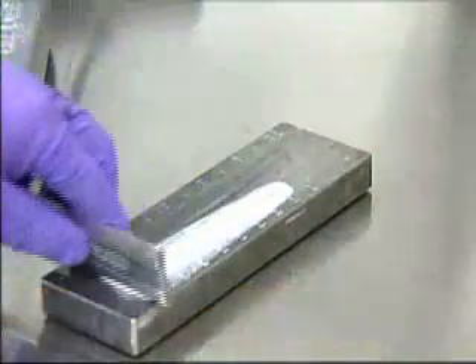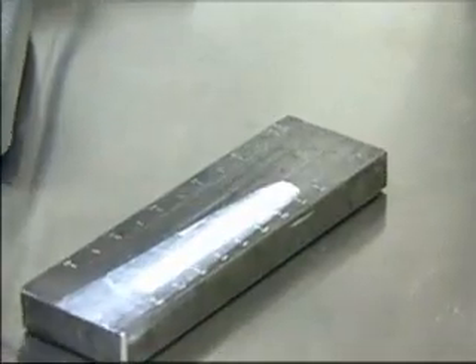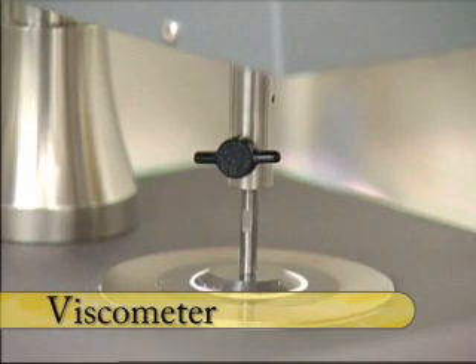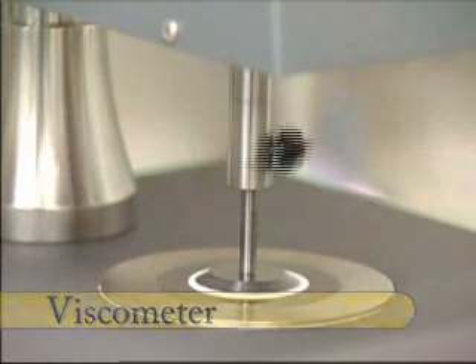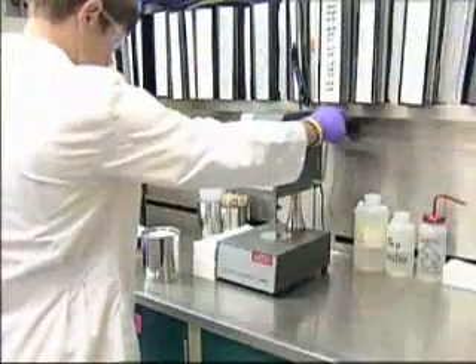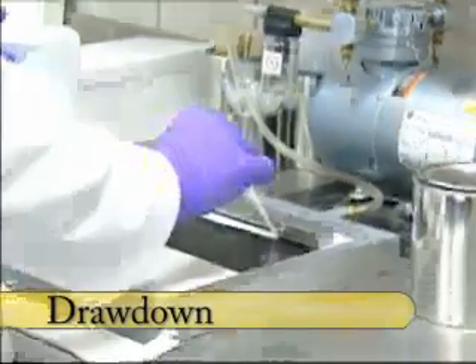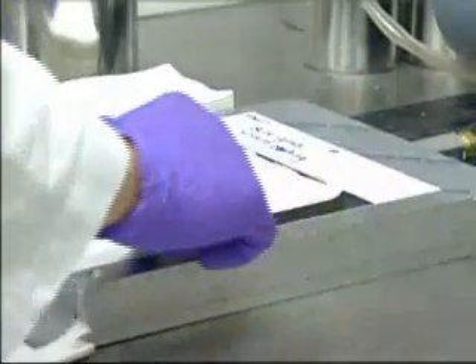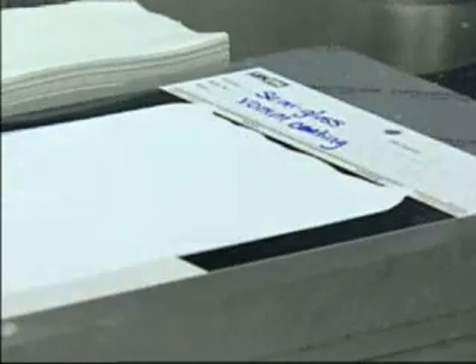A Hegman gauge is then used to determine the fineness of the pigment dispersion. Coating viscosity is determined using an ICI cone and plate viscometer for high shear rheology. The finished coating is applied onto Leneta charts and scrub charts for evaluation.